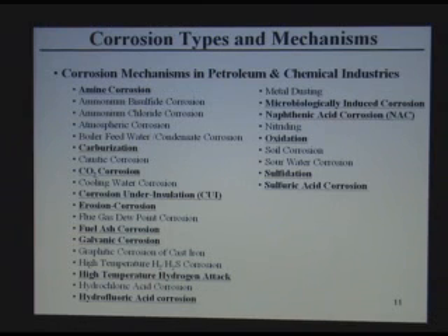crude units. Nitriding, this is also a phenomenon in ammonia plants where you have a lot of nitrogen at high temperature, and nitrogen reacts with the steel and produces nitrides, which make the metal very brittle. Oxidation, of course, high temperature corrosion by oxygen. Soil side corrosion, in underground structures. Sour water corrosion, wherever we have sour water can have corrosion. Sulfidation, where we have hydrogen sulfide at high temperature causing corrosion. Sulfuric acid, of course, causes a lot of corrosion.